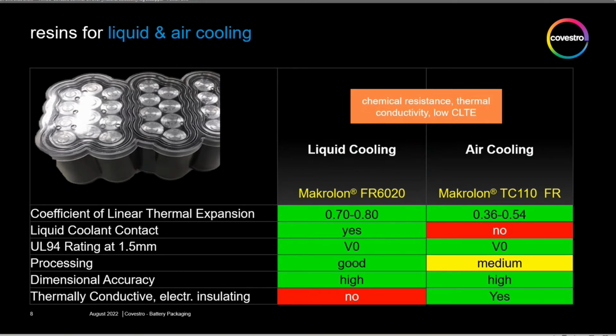So the next area is the liquid and air cooling systems. These are much different systems, I would say much more complex because there's multiple ways that you can cool a battery. You can use a liquid cooling system where essentially you will transfer a cooling fluid around the batteries so it won't come in contact with the batteries. Essentially, it'll be next to the battery through a layer of polycarbonate. So if you put this coolant fluid close to the batteries, it'll pull heat out of the battery and allow it to cool down. So those type of liquid cooling systems often require good thermal conductivity.